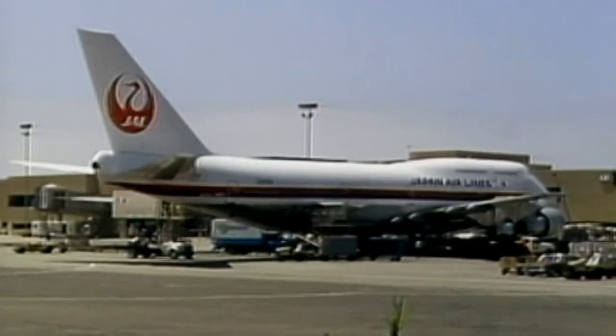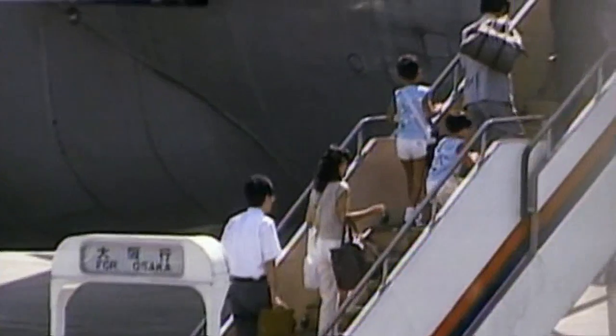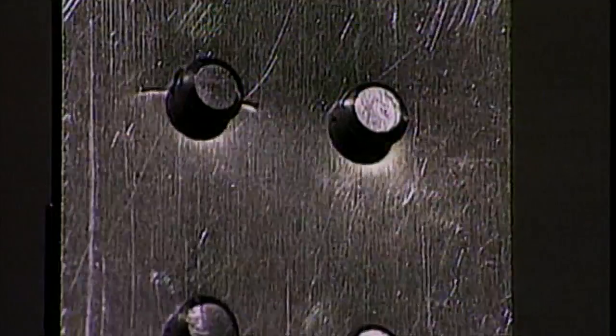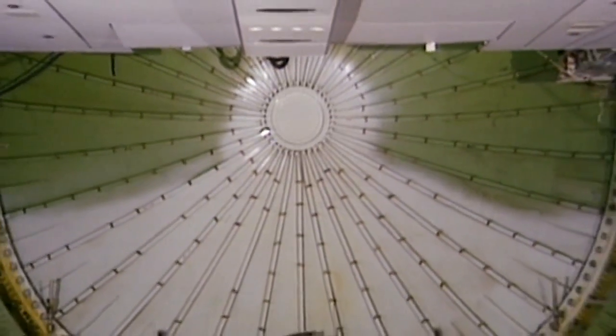Especially because this was such a busy jet. This particular airplane was used in Japan on a domestic operation, so it made multiple takeoffs and landings on domestic operations, unlike most 747s that make long-range hauls. So this was considered a high-cycle airplane. Investigators calculate that with the repair job, the bulkhead would survive approximately 10,000 flights or cycles. But on the day of the crash, the 747 had already racked up over 12,000 cycles.